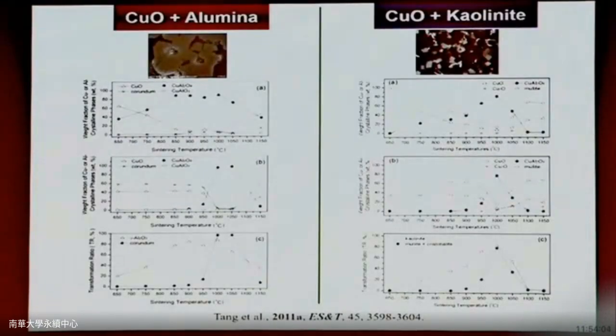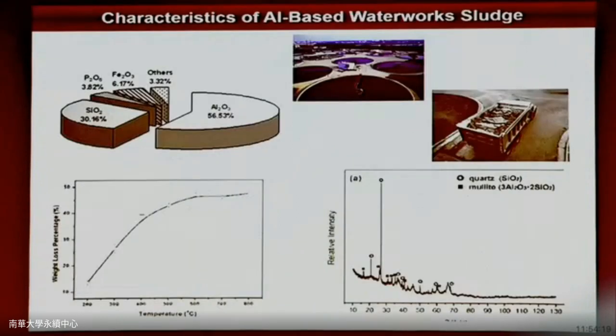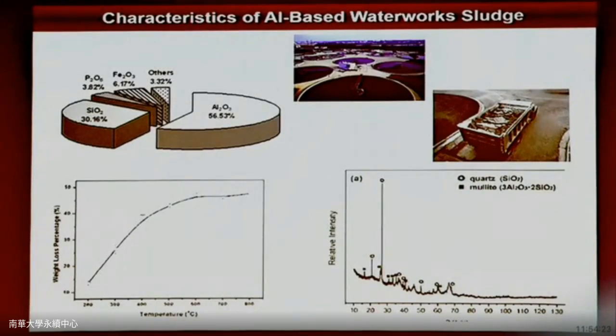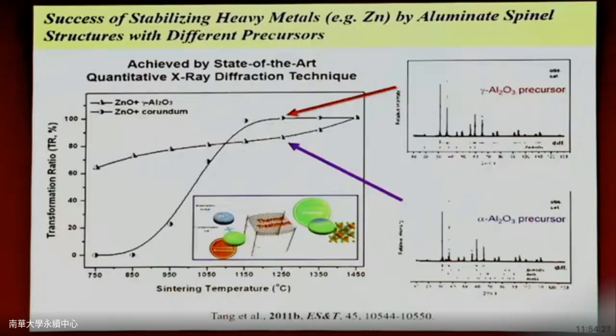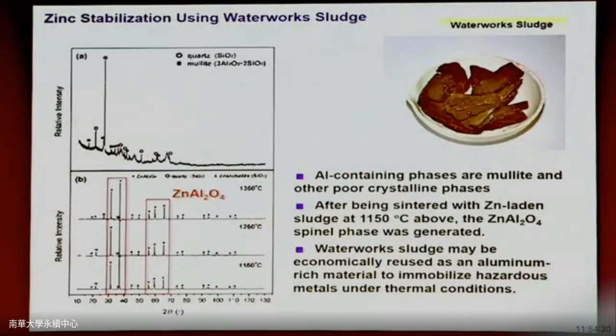So we did the copper, we did the copper aluminum system, copper clay system. We always find out there's a very, very good window that you can operate your process nicely in order to have a good result coming out. We started looking for all this kind of real waste, combined that, and saw whether it really came out as what we have in the lab, and it matched actually nicely.